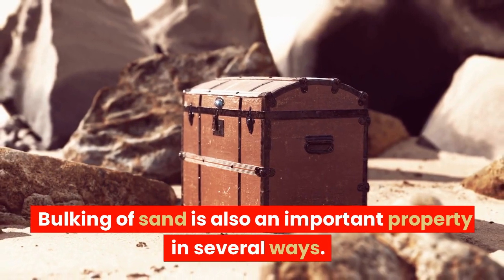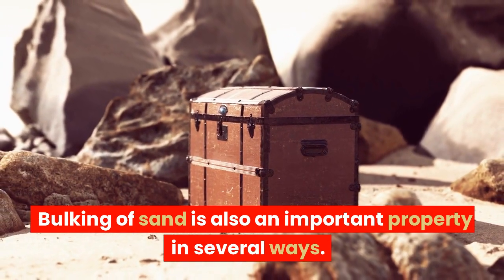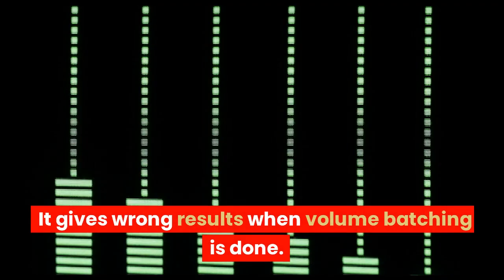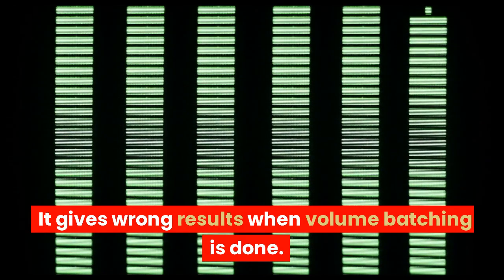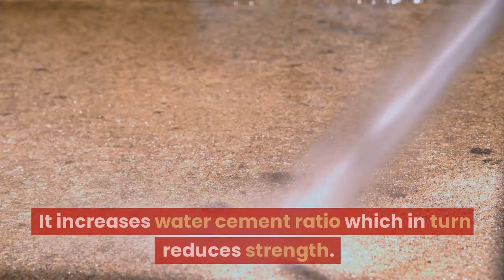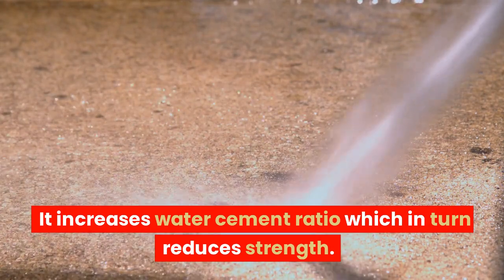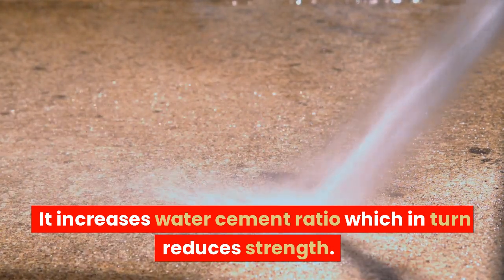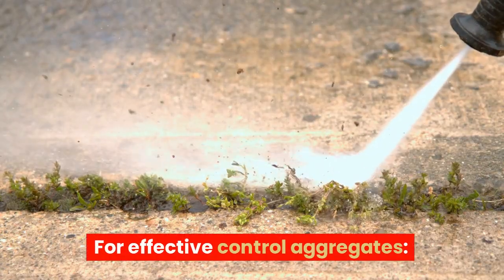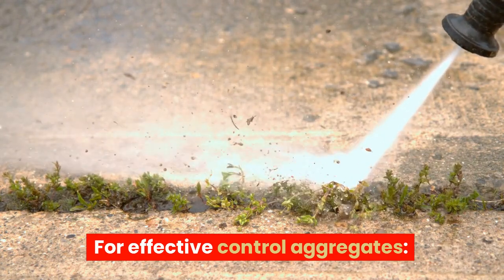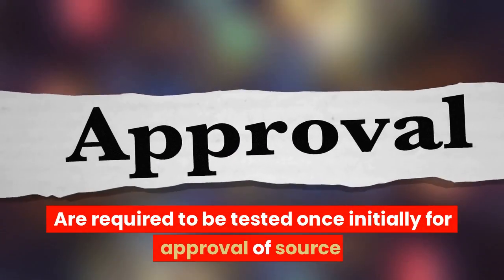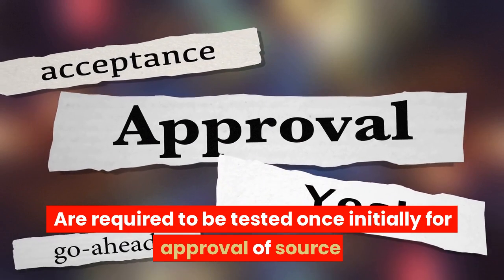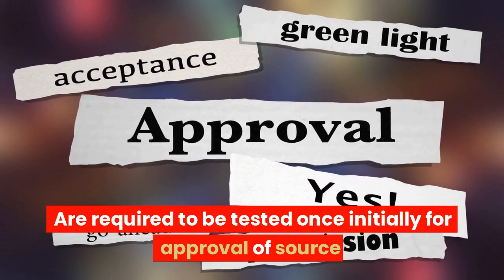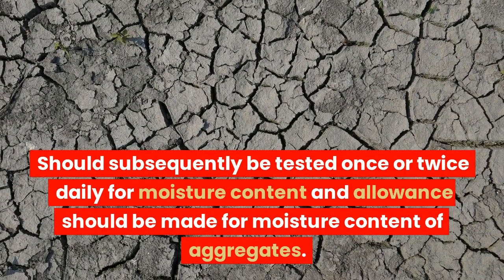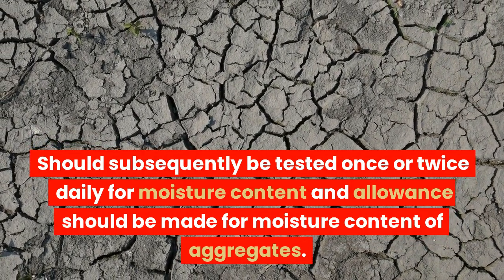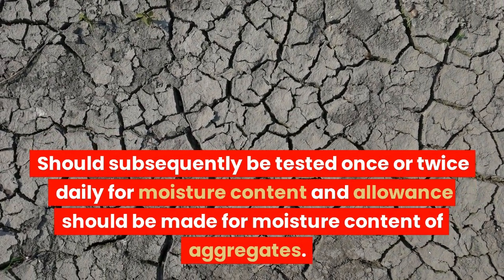Bulking of sand is also an important property in several ways. It gives wrong results when volume batching is done. It increases water-cement ratio, which in turn reduces strength. For effective control, aggregates are required to be tested once initially for approval of source. They should subsequently be tested once or twice daily for moisture content, and allowance should be made for moisture content of aggregates.